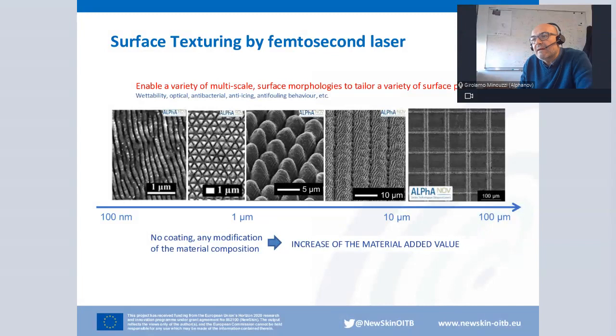What is interesting is that every different morphology that we develop on the surface can induce a different surface property, so functionalize the surface in a different way. We cite here some of the key properties that we can generate on the surface. So we can have a surface that turns out to be super hydrophobic, or that can absorb light, or that can show antibacterial effects, or that can have anti-icing properties, anti-fouling behavior, and so on. And interestingly, there is no coating, so there is no modification of the material composition of the surface, meaning that we increase the material added value in a way.